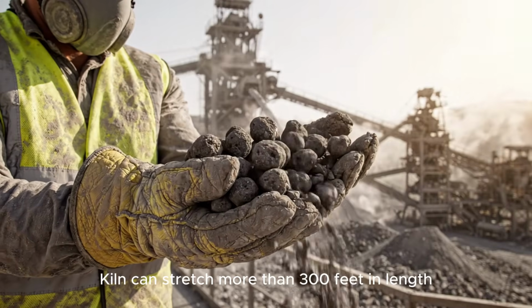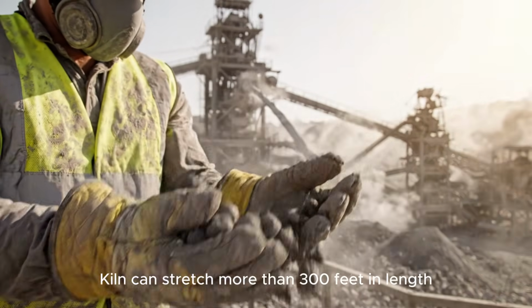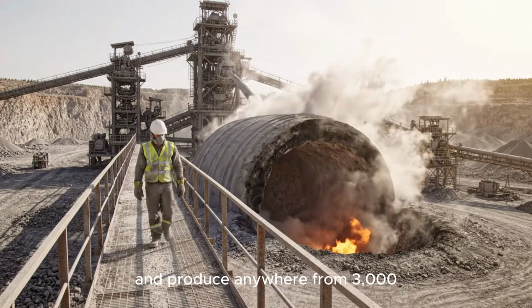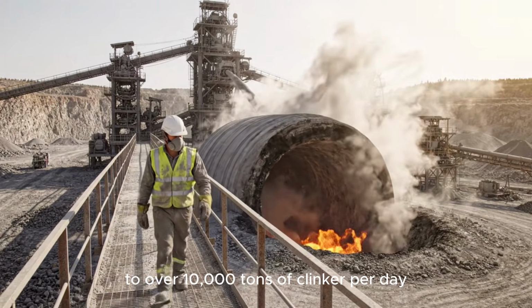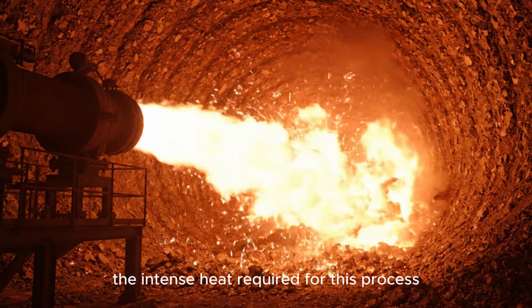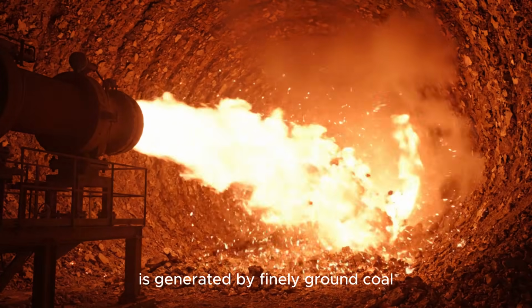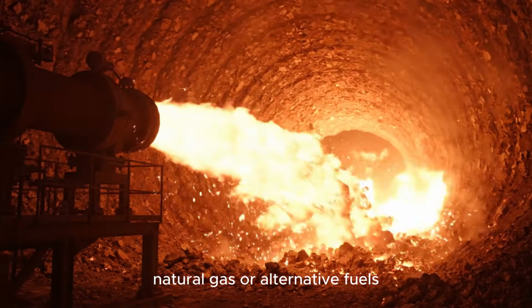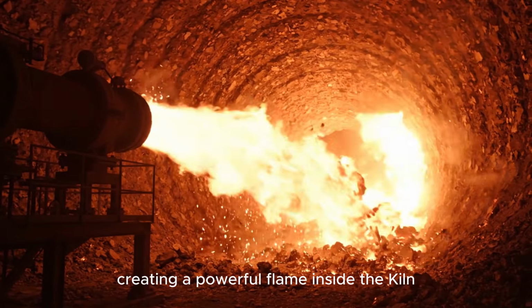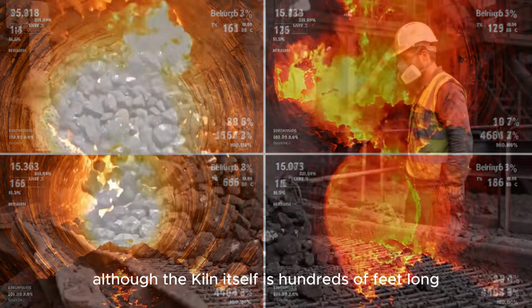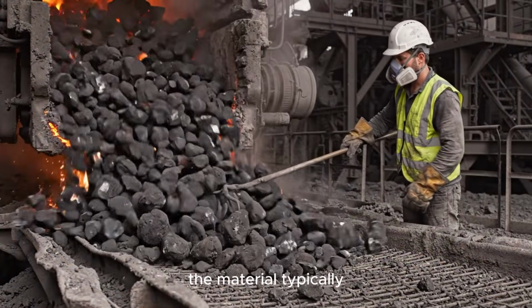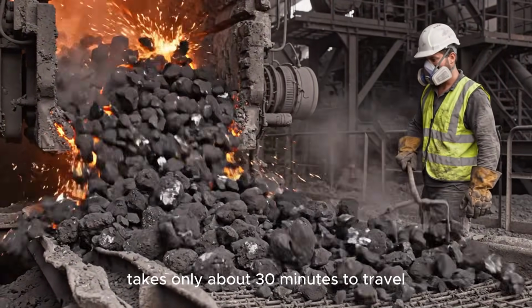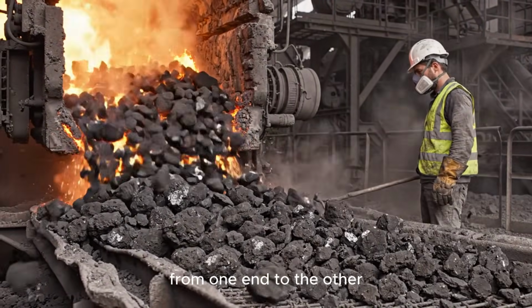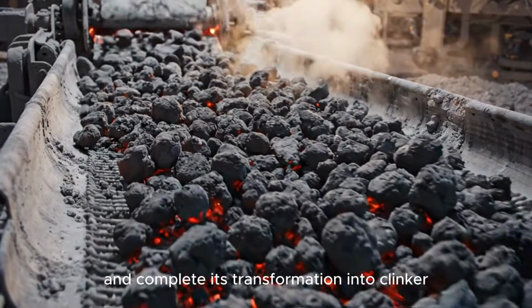A modern rotary kiln can stretch more than 300 feet in length and produce anywhere from 3,000 to over 10,000 tons of clinker per day. The intense heat required for this process is generated by finely ground coal, natural gas, or alternative fuels, creating a powerful flame inside the kiln. Although the kiln itself is hundreds of feet long, the material typically takes only about 30 minutes to travel from one end to the other and complete its transformation into clinker.